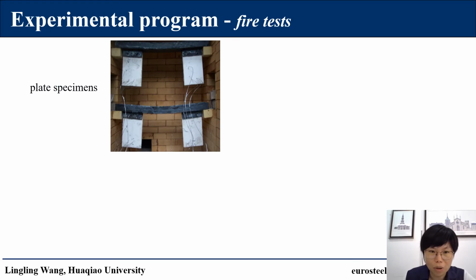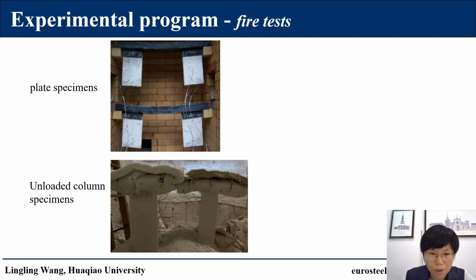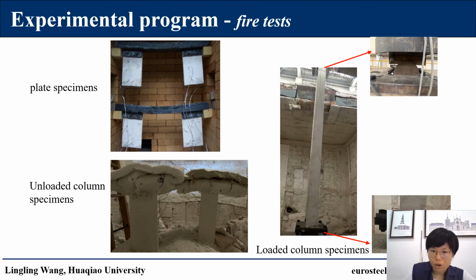The plate specimens were tested together and were hung vertically on steel beams inside the furnace. Each unloaded column specimen was placed on a block of concrete inside the furnace. The 4 loaded column specimens were pin-ended, and a compressive load was applied at the center of the cross-section. Before fire testing, each column was loaded to reach a load ratio of 30%, and the mechanical loading condition was maintained during the fire test.